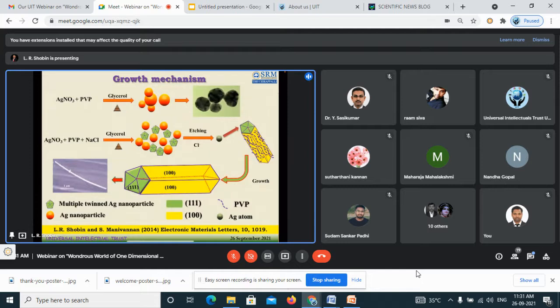So with these experiments and various results like the TEM and the SEM measurements, we are able to conclude this growth something like this. So what I have over here is silver nitrate, which is a silver precursor. Then I have polyvinyl pyrrolidone as PVP, and I have taken glycerol as a medium, and I am heating it around 150 degrees. What you will get is silver nanoparticles actually. These are all the particles where no NaCl is used. NaCl is absent over here.